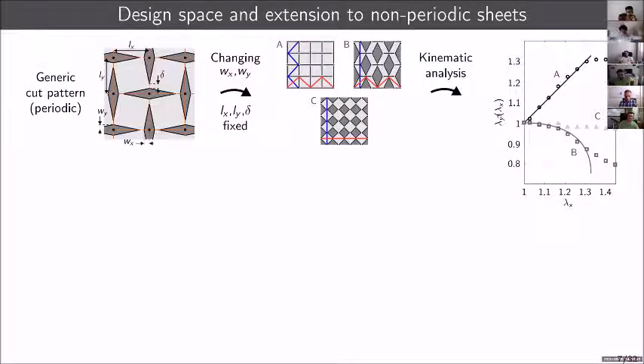So we apply a stretch, we take a sheet, we apply a stretch along the horizontal direction, and we measure what is the stretch along the vertical direction. And the dots correspond to experiments, while the continuous lines correspond to kinematic models. What you can see is that the sheet, the structure A, has a negative Poisson's ratio. And you can see that because the stretch is greater than one along the horizontal direction and greater than one along the vertical direction. On the other hand, the pattern in B presents a positive Poisson's ratio, and you can see that both B and A have really large deformations.